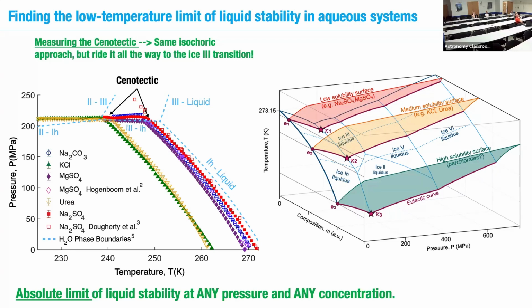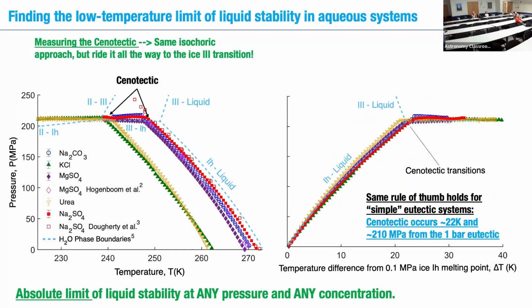And this is intriguing because these things might have really, really low cenotectic temperatures given the slope of this ice 1, ice 2 liquidus curve as you keep going down in temperature. So something to look at. Increasingly difficult, I'll note, to measure the cenotectic experimentally as it occurs at lower and lower temperatures, just because the kinetics of the solid-solid phase transitions in the system get really sluggish. We're working on new ultrasonication methods to speed these things up, but it's challenging as you go to lower temperatures to do any of this phase transition analysis.